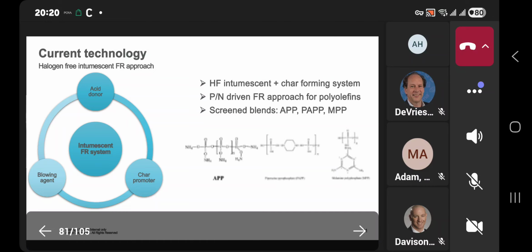Our current technology development is based on a halogen-free intumescent system with char-forming behavior, using a phosphorus-nitrogen-driven approach for polyolefins, especially for PP. Since our customer requests are coming for non-halogenated systems, we tried different NHFR systems and saw that, depending on the customer process, the color of the parts, the wall thicknesses, the geometries, and the volume of their machine can affect the performance of the materials. So these items directed us to use different combinations in different formulations. So currently we have a set of solutions for several customer requirements.